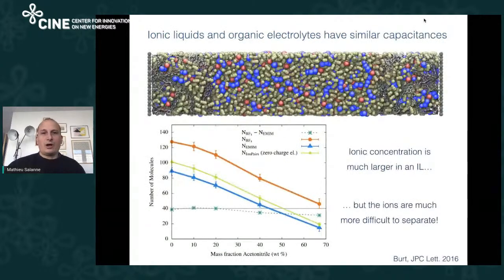Then the second important question was what is the best electrolyte. And in fact, there was a lot of hope that ionic liquids would be perfect electrolytes because they have a large concentration of ions. But the experimental results were not so convincing. So in this study, what we made is to change the concentration of ions inside an organic solvent, which is acetonitrile. And here, in fact, you have a very interesting feature.